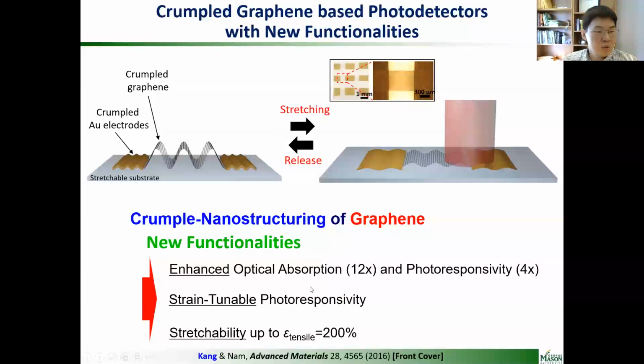As we create these nanostructures, we can enhance the material's properties. For example, because graphene is very thin, it absorbs only a small amount of light, so it looks very transparent, like you see here. But as we create these nanostructures, this material can absorb more than an order of magnitude more light. And we use this structured nanomaterial graphene for photosensors. These graphene materials can sense and detect light: when light is shone on these materials, electrons are generated and flow. By detecting the number of electrons generated by the light, we can detect the light intensity.